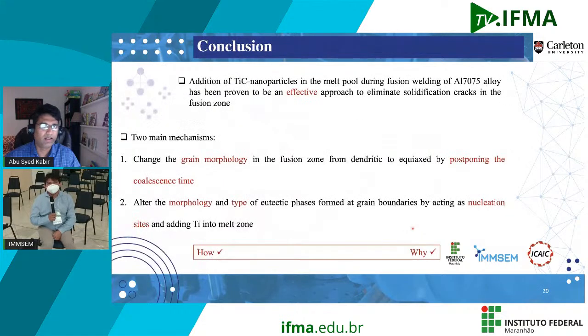Okay, so let's come to the conclusion. We found that the titanium carbide nanoparticles in the fusion zone were effective in eliminating solidification cracks, and we proposed 2 mechanisms for this. One mechanism is that the presence of titanium carbide changes the grain morphology from dendritic to equiaxed, and it changes the morphology of the secondary phase as well.